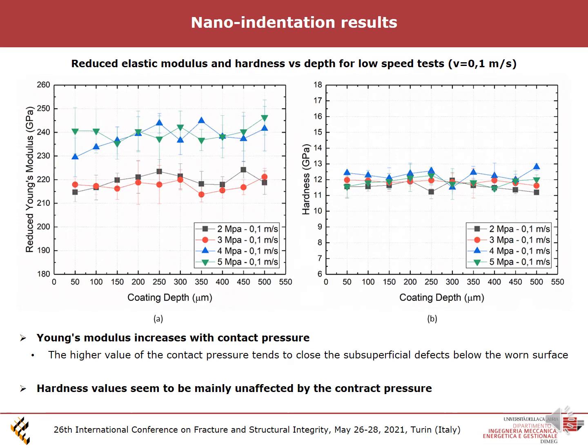The nano-indentation measurements carried out on the cross-section of the samples tested under low sliding speed condition, that is 0.1 meter per second, highlight an almost flat trend for both elastic and hardness responses as a function of the coating depth. However, it's interesting to note that the reduced Young modulus is lower in the samples tested at contact pressures of 2 and 3 MPa compared to the case of 4 and 5 MPa, varying from around 218 to 238 GPa.